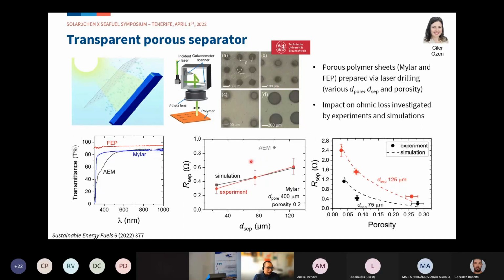First, shown here is the separator resistance, or the ohmic loss. The simulations and experiments agree pretty well as a function of thickness as well as porosity, and the ohmic loss is shown to be lower than what we get with an anionic exchange membrane. So the ohmic loss is one factor.